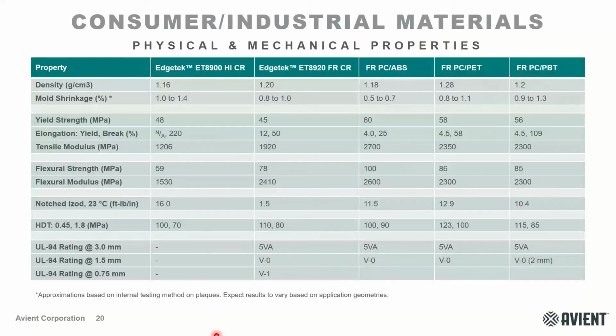And then a quick overview again of the physical and mechanical properties, essentially the same thing as for the healthcare slide. So in the consumer space, now we have our high impact grade that has a little bit higher mold shrink relative to some of these other ones. But when you're looking at the tensile and flexural properties, again, pretty comparable across the board. Again, these are all FR incumbent materials, so it's a little bit more direct comparison to these, or the ET 8900, 8920 grade, I should say. But one thing I did want to highlight is that for a semi-crystalline material, the notched Izod performance can be lacking at times.